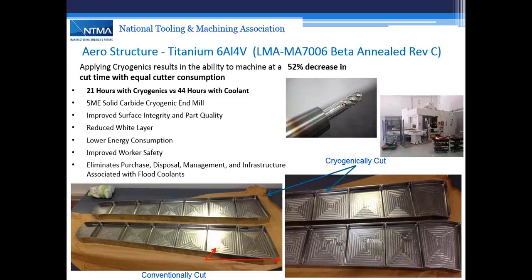And then what we did is we coached and worked with the programmer and enabled the higher surface footages, adjustments in radial and axial to accommodate what we want to see with cryogenic machining. And we were able to reduce the cycle time down to 21 hours. That's more than 50% reduction in cycle time.